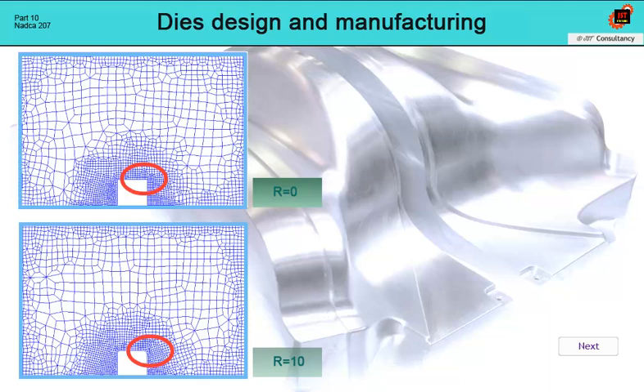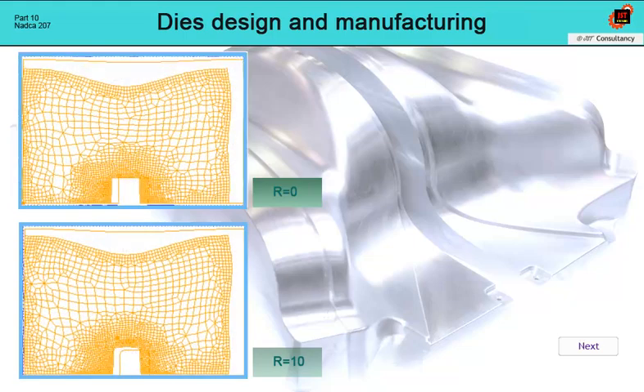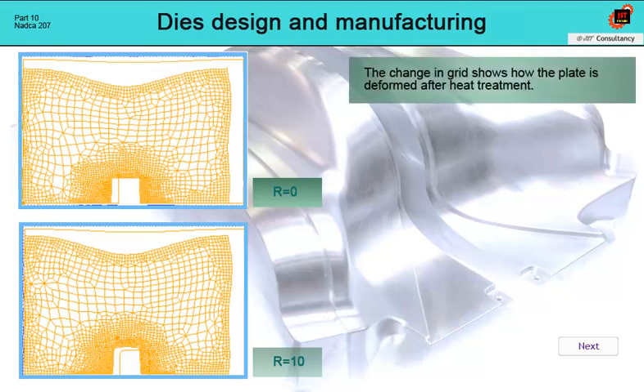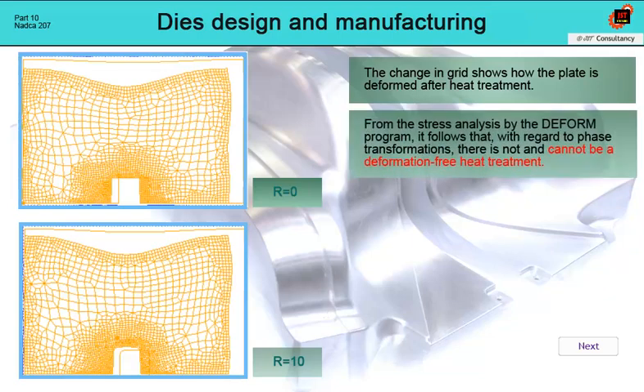The initial state at a temperature of 1050 degrees Celsius is shown in blue. The final state is shown in ochre color. A comparison of both shapes shows how the plate deforms during cooling. It can already be seen from this illustrative example that deformation-free processing we cannot expect. The reason is the phase transformation and volume change from austenite to martensite, and at the same time, the stress resulting from the temperature difference.